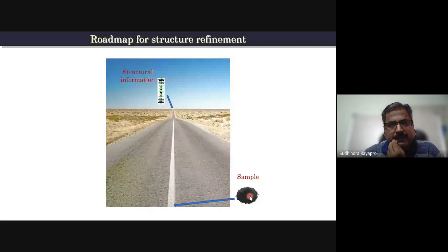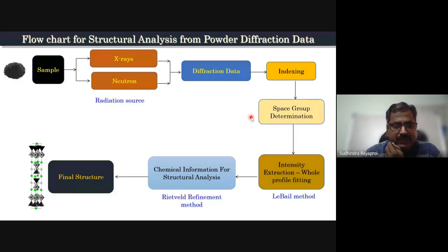Okay, so the roadmap actually starts from your sample, which is a powder, probably a black powder, and our aim is to reach the structure. So what is the route we have to take? The first is, once you prepare the sample, a well-ground powder sample, you look for the radiation source. You can choose X-rays or neutrons. Okay, and based on that, you collect your diffraction data. You carry out what is called indexing, and determine the space group.